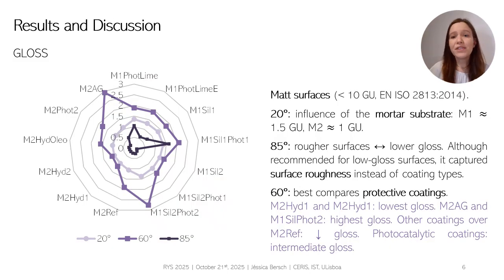Surface gloss can be measured using different geometries. In this study, for the three geometries studied, all the surfaces were classified as matte because they presented less than 10 gloss units. Regarding the different geometries, 20 degrees, which is the lightest purple curve, showed mostly the influence of the mortar substrates, with M1 presenting around 1.5 gloss units and M2 configurations 1 gloss unit.